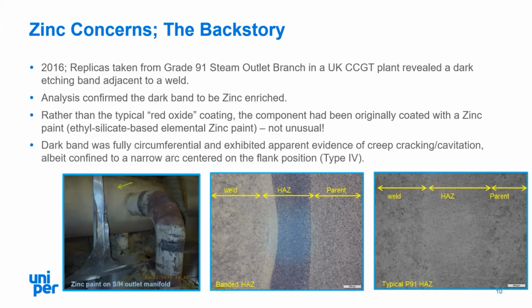The dark band itself was fully circumferential around this weld, and there were also signs, when the replicas were examined, of creep cracking and cavitation, all within this dark band, and also at the flank position, the type 4 position, which Jeff mentioned earlier, where you'd expect creep damage to develop. But this was decidedly premature and not really seen on other plant.